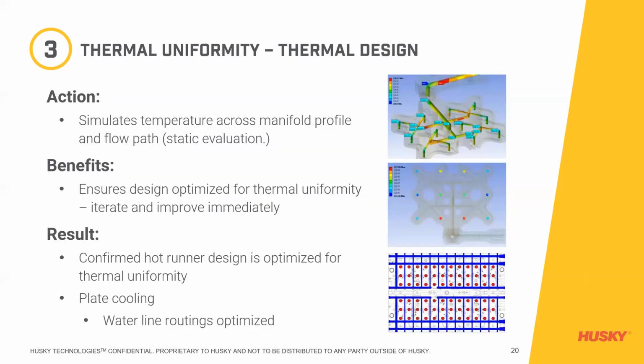Next is thermal uniformity. What we want to do with thermal uniformity is Husky performs a FEA, or a thermal finite element analysis, which gives us a good indication of what the manifold temperature variation is going to be based on the specific design. By adjusting the heater wrap, the number of heater zones, thermocouple placement, melt channel layout, heat sinks, and manifold profile, the designer can optimize that thermal uniformity of the system prior to releasing it to manufacturing, again using finite element analysis, or FEA, to help with that process.